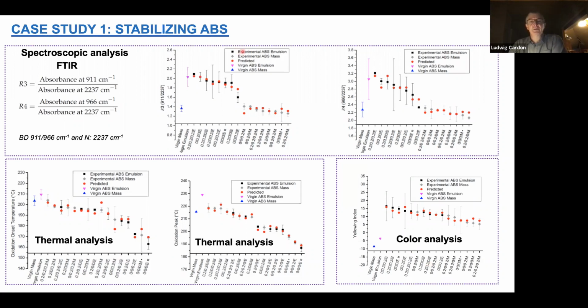We start, as you can see on the top of the slide, with on one side the ABS made by emulsion polymerization and the other one by mass polymerization. So we selected the two types of ABS for polymer processing. We did modeling, predicting what we normally could expect due to the type of blend. We are also applying the effect on the aging, on the antioxidation, let's say, or the oxidation. You can see here the virgin materials. We also did experimental blending with two types of antioxidants. And then we found out how the reaction of the material was interfering depending on the processing parameters. So this is one of the examples of material improvement we want to achieve.